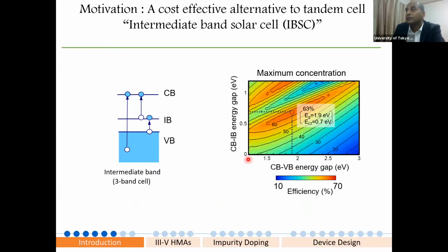And this is a thermodynamic calculation for the case where we can allow an intermediate band, IB, between the valence band and the conduction band. The horizontal axis is the band gap between the conduction band and the valence band. With different combinations of band gaps, the maximum is 63% when your band gap is 1.9 electron volt and you have an intermediate band at around 0.7 electron volt. If you bring this kind of combination and make your p-n junction, you can make an intermediate band solar cell.